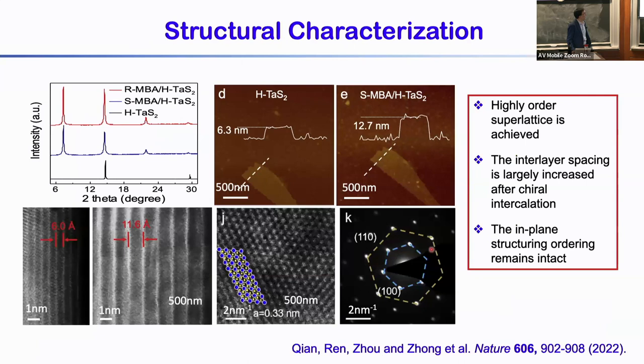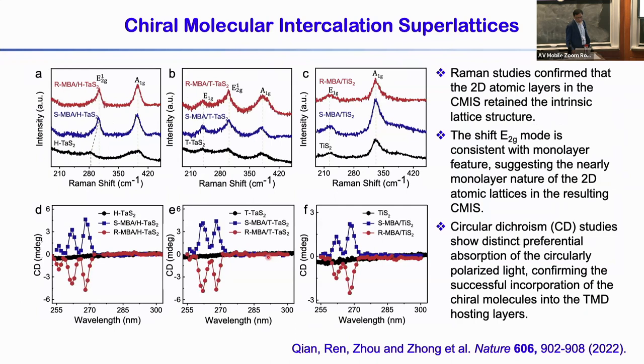The intercalation process is rather straightforward. After intercalation, we can see clear lattice expansion from the pristine to the intercalated material — the thickness almost doubles, while the intrinsic crystal structure of the 2D material is maintained. Looking at the Raman spectrum, after intercalation we have stronger Raman resonance, probably indicating stronger electron-phonon interaction in this monolayer structure. Looking at circular dichroism, which characterizes chirality, we can see that after intercalation we receive clear CD signals that confirm the chiral molecules are intercalated between these atomic layers and their chirality is maintained in the superlattice structure.